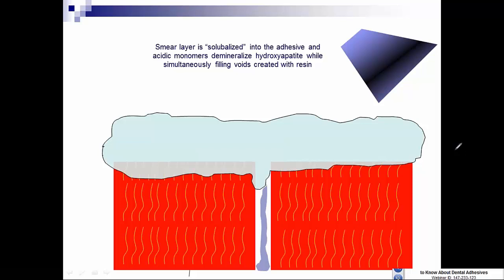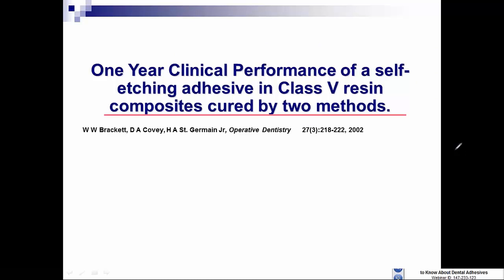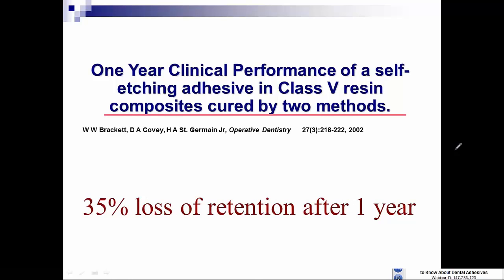So the cavity preparation has to be very careful about residual debris when using a self-etching adhesive system. In addition, all of these systems contain water. And unlike acetone or ethanol or even tertiary butanol, drying water out after application is much more difficult because those other solvents are much more volatile. So in the beginning, and this was a clinical study done with Prompt L-Pop, 35% of the restorations fell out after 1 year. So the early self-etching adhesives, while state-of-the-art, never became standard of care because they never became clinically